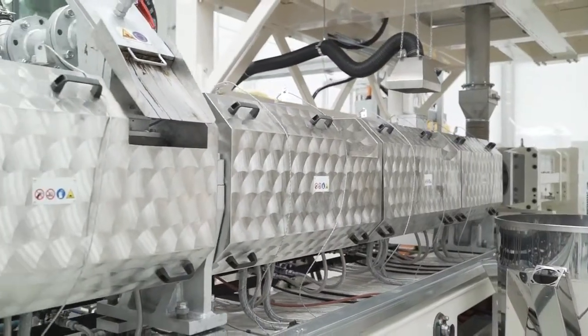The absolute elimination of VOC and the recycled material odor is not achievable in the extrusion, regardless of the kind of process. This is why Bandera offers a patented pellet post-treatment to eliminate VOC and complete the upcycling process. The configuration of this continuous system can be in line with pelletizing or offline to process material independently.